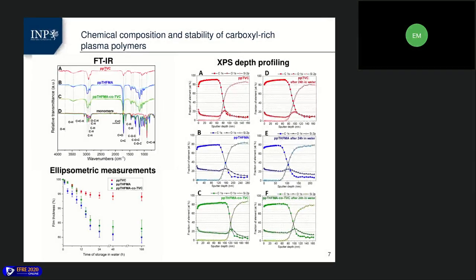As all of the biochemical procedures are carried out in an aqueous environment, the obtained plasma polymer films have to show a good level of stability upon immersion in water. In our study, we carried out analysis of the films right after the deposition process and after 24 hours of storage in water. FTIR analysis revealed the functional chemical groups present in the films and helped to follow chemical changes after storage in water. FTIR of the monomers were recorded to be able to compare chemical composition of the resulting films with the corresponding non-polymerized monomers.